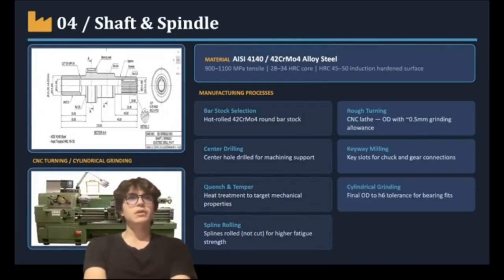The shaft, or spindle, transmits the rotational torque from the gearbox to the chuck. It must withstand high torsional fatigue loads from repeated drilling operations. The material is AISI 4140 or 42CrMo4 chromium molybdenum alloy steel, which achieves a tensile strength of 900 to 1100 MPa after heat treatment. The core hardness is 28 to 34 HRC, while the surface is induction hardened to 45 to 50 HRC for wear resistance at bearing contact points.